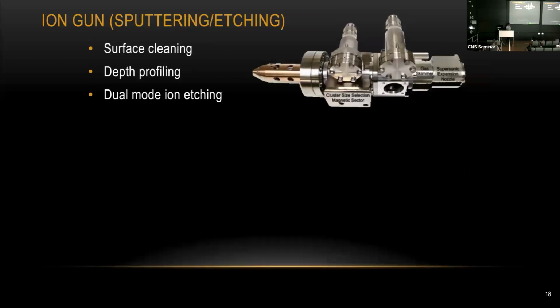Up to the last slide, I would say the XPS measurement is a non-destructive measurement. But once you try to use the ion gun, there is going to be some damage on the surface. We're going to do some sputtering, some people call it etching, milling, whatever you're going to call it. But anyway, you're going to do some damage on the surface of your material.